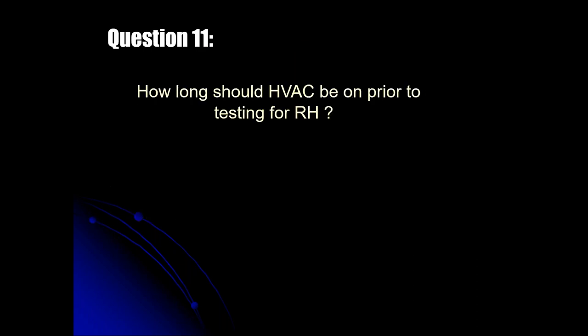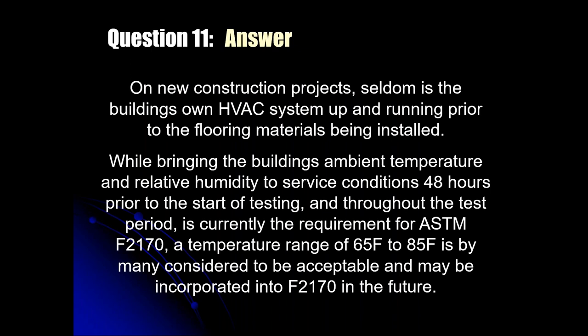Okay. Question 11. How long should the HVAC system be on prior to testing for RH? Currently, the ASTM F2170 test method for conducting concrete internal relative humidity says that the building has to be at service conditions. We're not quite sure how that got through. It is the ideal, without question, but for new construction, it's just seldom achievable. I do believe you're going to see us modify that to have a window of variance to that requirement. But for all of the moisture tests, whatever conditions are deemed necessary have to be established and verified 48 hours before we start and maintained throughout the test period.